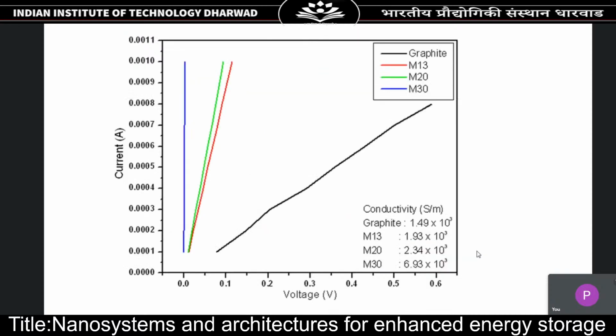This is the electronic conductivity of the various exfoliated graphene. You can see that graphite conductivity in Siemens per meter is only 1.4 into 10 raised to 3. If you go for 13 hours, the conductivity increases to 1.93. If you go for 20 hours, it increases to 2.34, and if you go for 30 hours, it increases to almost 7 into 10 raised to 3. That shows that the graphene is becoming more and more exfoliated and also pure. That is how it is able to retain its electrical conductivity property.